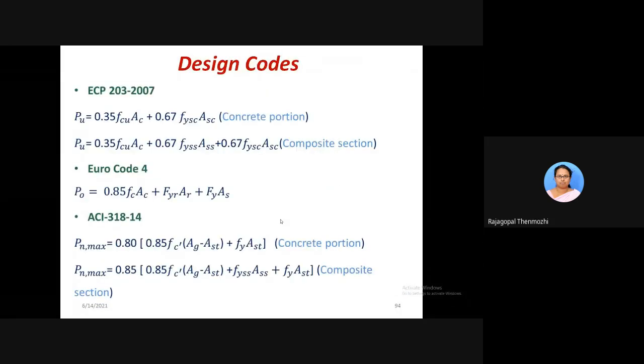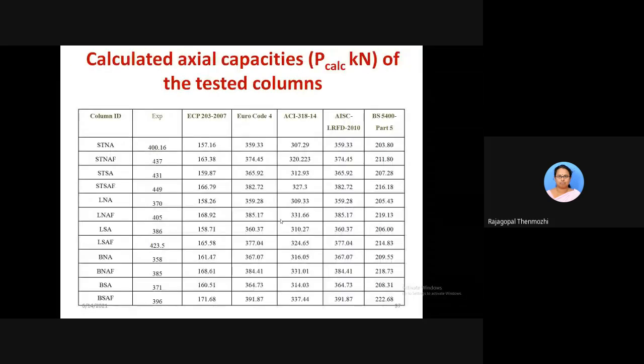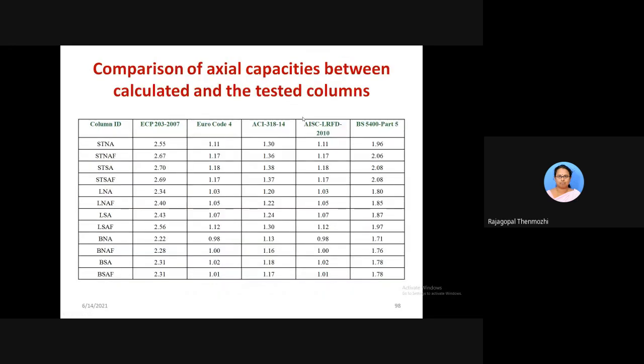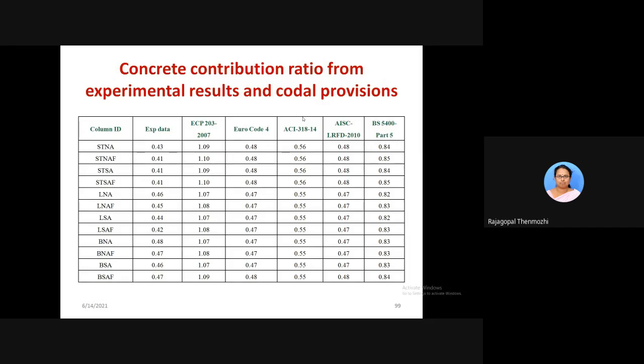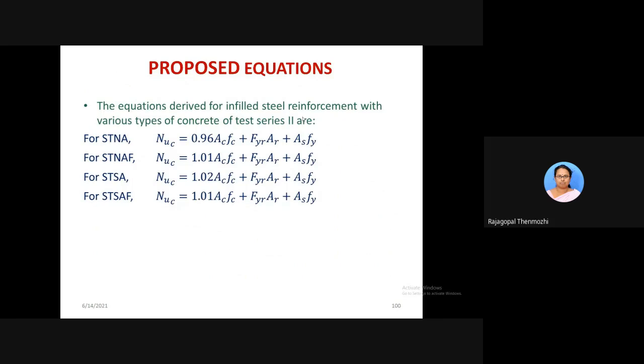We have made a theoretical analysis as per 5 different country codes, those values have been compared and presented. These are the experimental values. They have good coincidence with the Eurocode system, but the other codes are a little less conservative, so many differences in values we could get. EC4 and the AISC LRFD standards projected very good similarity and comparability. ACI code is a little bit lesser. But when you compare with the other codes, say BS 5950 part 5, BS 5400 part 5 and ECP, it is much more. So it agrees well with the EC4 and AISC LRFD standards. The deflection values and the ratios have been compared here. These are the theoretical proposed equations.